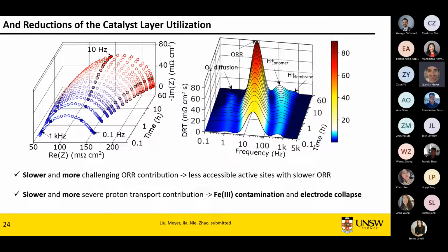Now, one problem you've got is the ORR has become much slower. So this is initially the overall ORR rate in the catalyst layer. It shifts to low frequencies. It also has a much higher resistance. Kind of reasons for this is first that you may have two types of active sites. So there is a trend in literature emerging that there are two types of active sites that you easily form when you make an electrochemical catalyst. One type is very active but highly thermodynamically unstable.